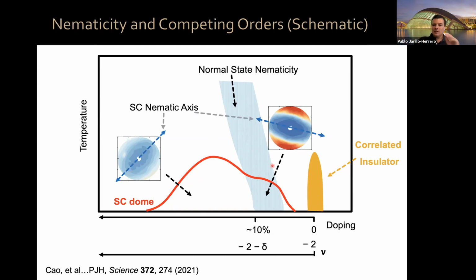So it seems that the superconducting state is nematic everywhere, but in the region where there is competition with this other nematic normal state phase, the superconducting order parameter's nematic axis gets set by that competing phase, which happens in this region. So if you want more details, you can look at this paper. I'm happy to answer questions about it.